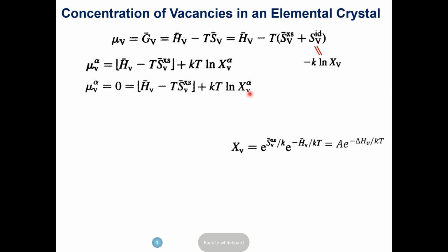By the way, this is the same quantity as that—since I'm using different sources, sometimes symbols are different, so this is the same as that. And you can see that when you set this equal to zero, it will give you this exponential term solved. It comes out that there is an enthalpic term, and the excess entropic term goes in here, which I'm replacing as a constant A. Why? Because this term does not depend on temperature—so the temperature dependence goes into the enthalpy term.